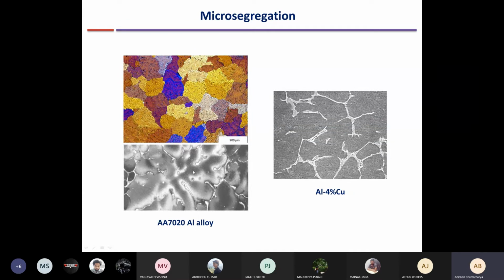Somewhere around there some nuclei must have formed, and then it grows in all directions. While it grows, the next solidification occurs with more and more concentration, and finally towards the grain boundary we have very high concentration. So actually these are eutectics at the grain boundaries. So this is how a real-life microstructure looks. Okay, this is from an